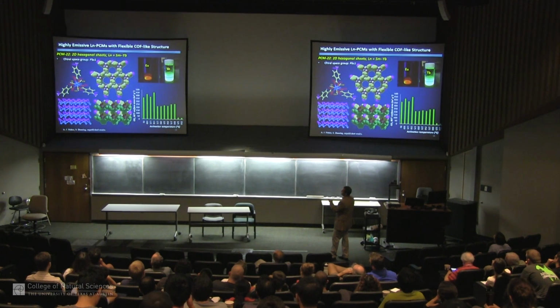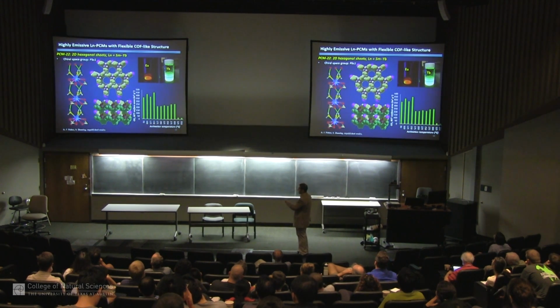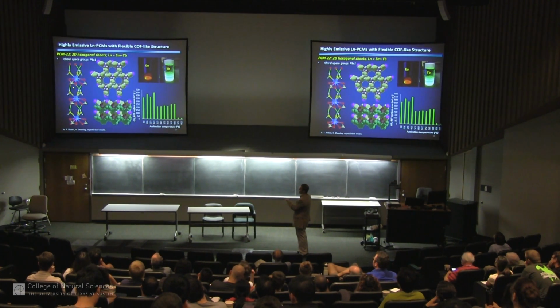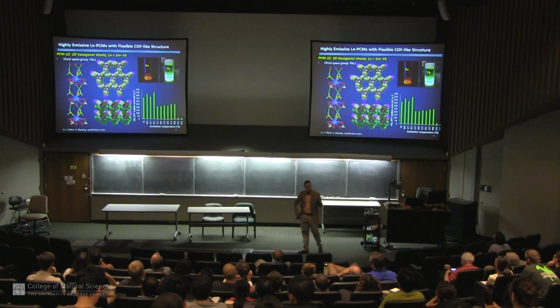And because we can put different lanthanides into the material, we can get different emissive colors in this case, and that can be useful for diagnostics. And this is why the layers are eclipsed. It's because between each sheet, and these are bonds between the layers, as shown in these green dashed bonds, we have very close range, a multitude of strong hydrogen bonding interactions that keep everything pinned together.